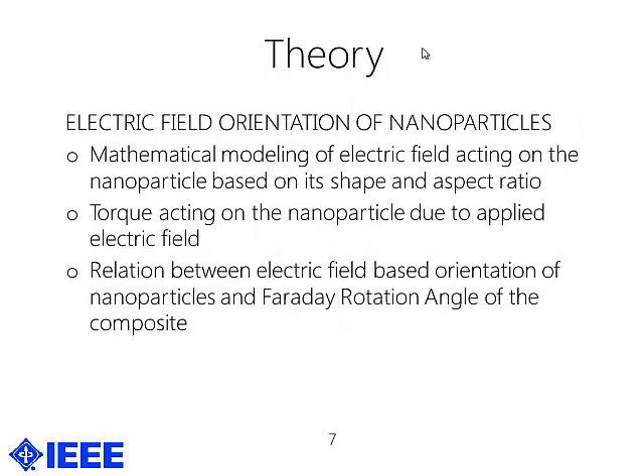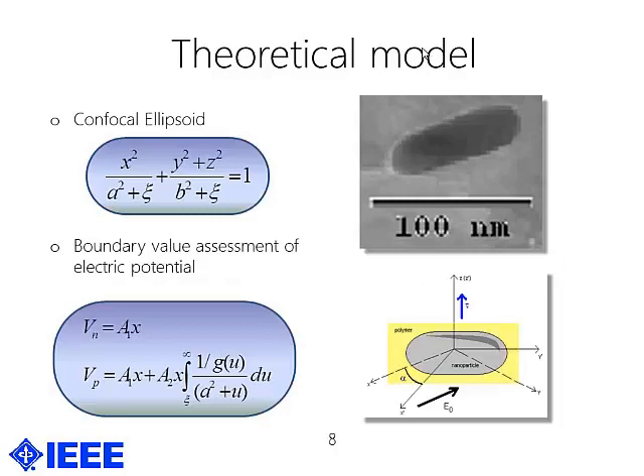So the electric field orientation of these nanoparticles. Now, we performed the mathematical modeling of how the electric field acting on this particular composite would move around the nanoparticle inside the polymer matrix. So there's going to be a torque that's acting on the nanoparticle due to the applied electric field, and we computed the relation between electric field based orientation and how it affects the Faraday rotation angle of the whole composite itself. So the nanoparticles that we used in this particular study, they're confocal ellipsoids with an aspect ratio of 3:1,